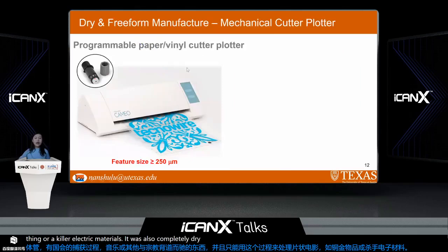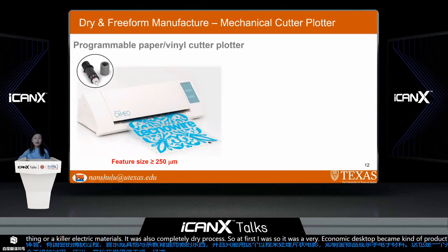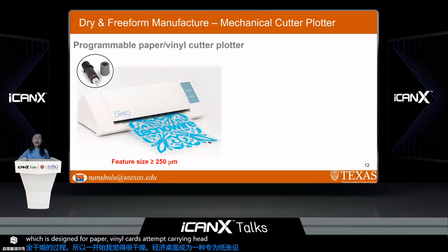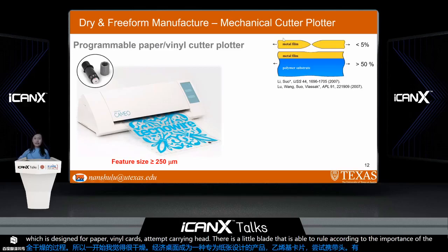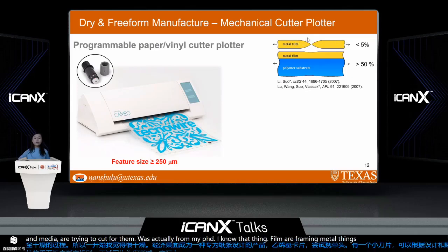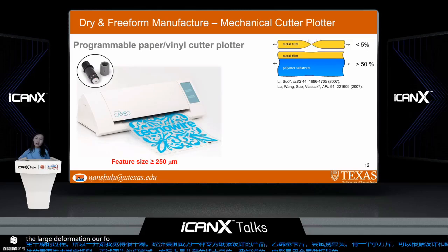So at first, we started with a very economic desktop mechanical cutter plotter, which is designed for paper and vinyl cuts. And at the tip of this cutting head, there is a little blade that is able to move according to the imported design patterns. And we immediately tried to cut, for example, aluminum foils. But actually from my PhD study, I know that those freestanding metal thin films are not very stretchable because all the large deformation is focused at this single neck. So the global stretchability is very limited.